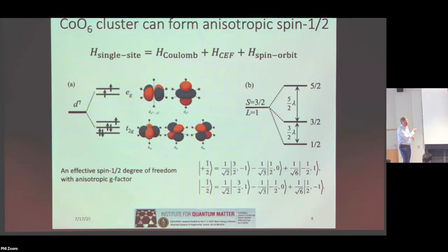If I had isotropic conditions, it would be degenerate, but now it's split into a triplet and a doublet, and with 7 electrons to fill into this state, I end up with a triplet ground state orbitally, and then I'll have a spin 3/2 spin degree of freedom. But now, because of spin-orbit interaction, this degeneracy that would otherwise exist is resolved, or lifted, into a spin 1/2, spin 3/2, spin 5/2.